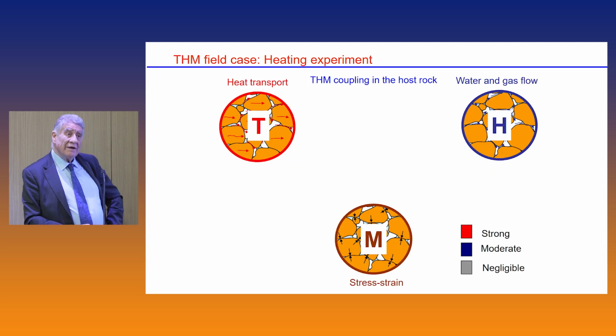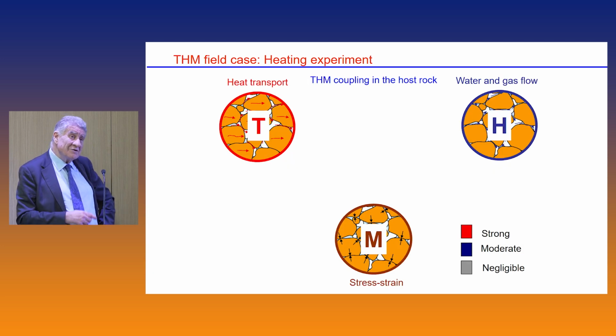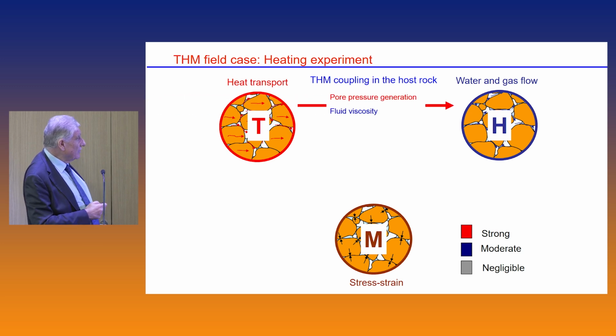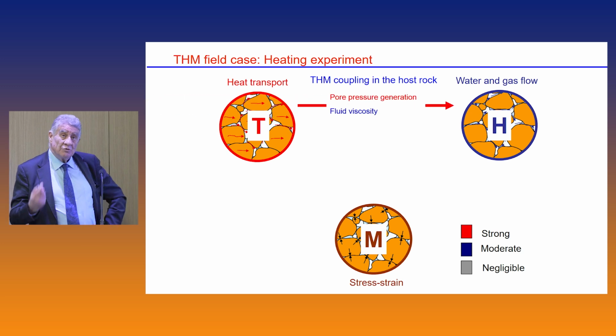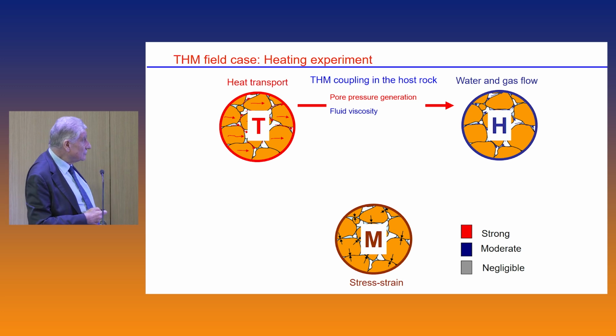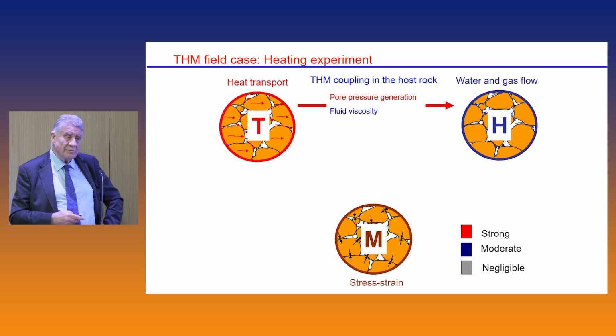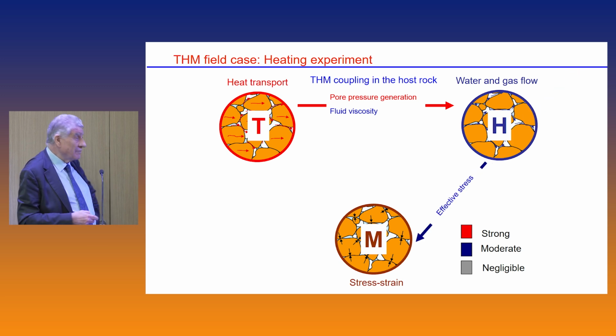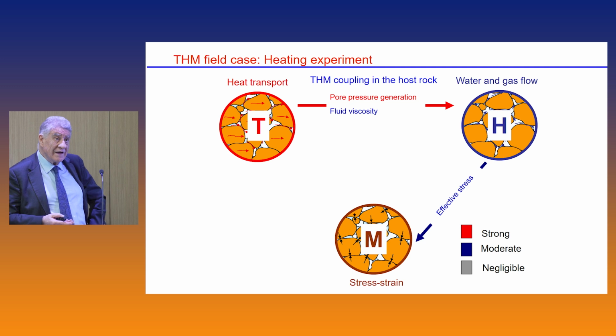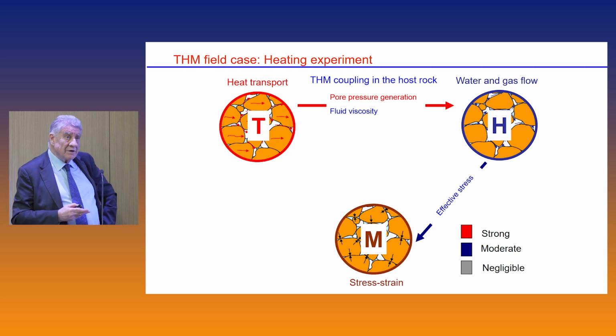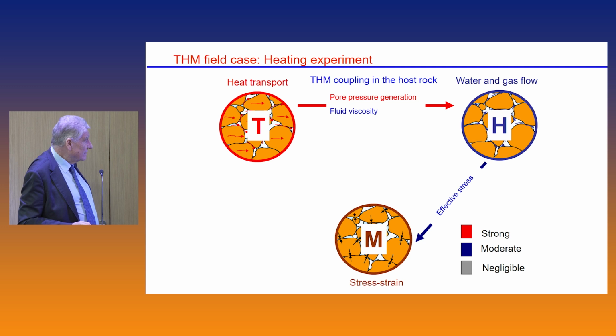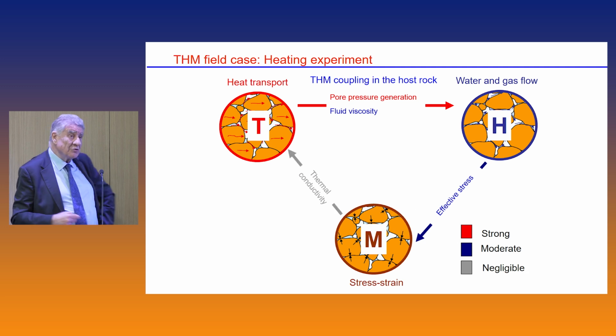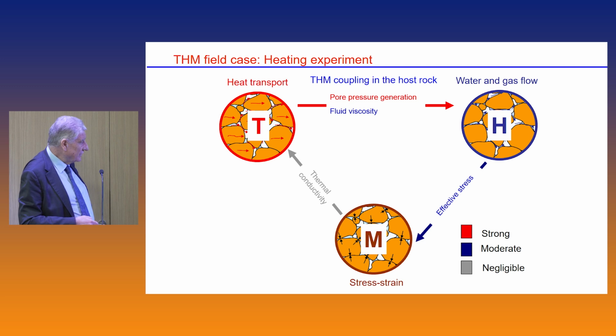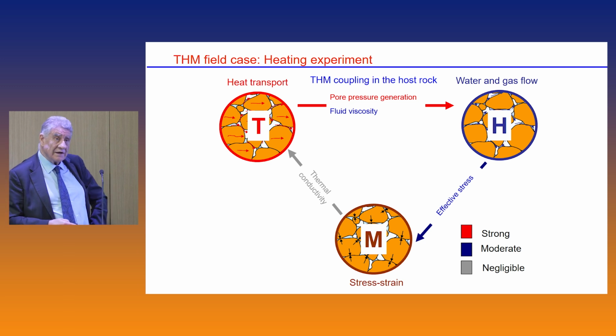One of the advantages of using numerical analysis is that you can look in detail at the results. So you can, for instance, look at the couplings and see whether they are strong, moderate, negligible. If we go from thermal to hydraulic, due to this pore pressure generation, there is a strong coupling. Also some more moderate coupling due to the changes in fluid viscosity. From hydraulic to mechanics, obviously there are changes in effective stress, so there is a mechanical effect. But it's moderate because these materials are stiff and they don't deform very much. And because they don't deform, the thermal conductivity is more or less constant, and therefore the coupling from mechanical to thermal is actually negligible.